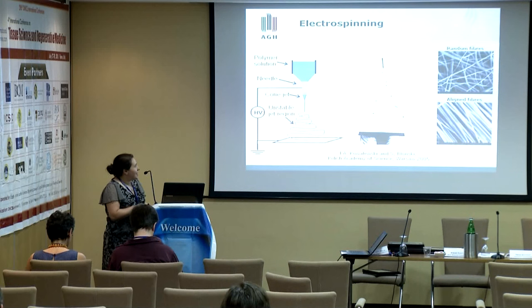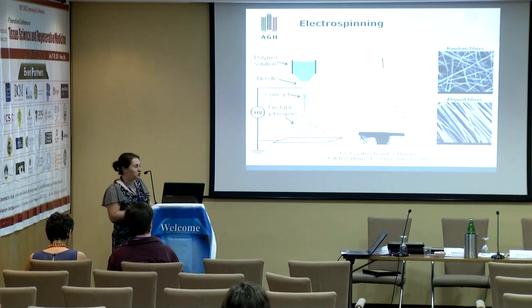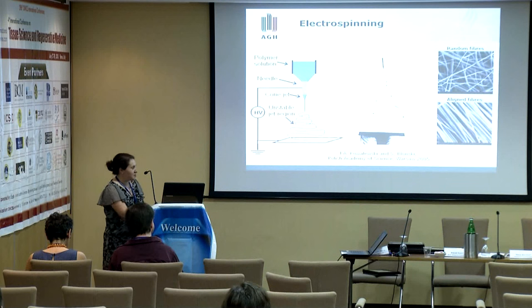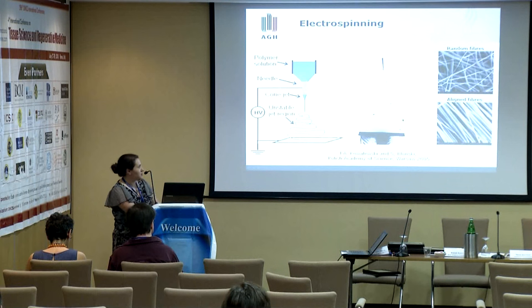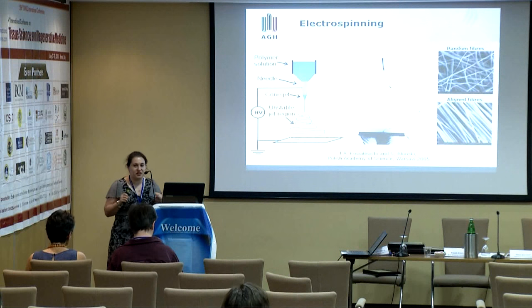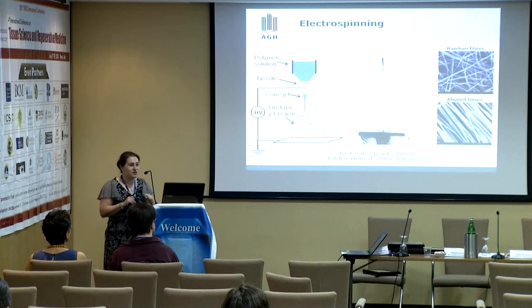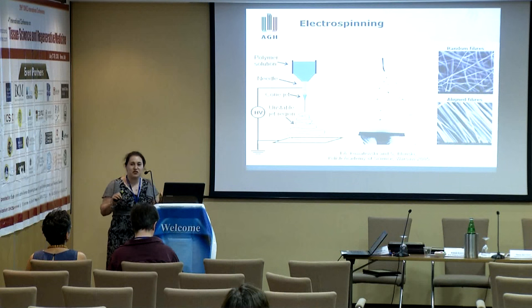We push the polymer solution through a nozzle where we apply high voltage, and due to electrostatic forces we have formation of the cone jet and the spinning region. During the spinning region there is a stretching of the jet, and during the stretching the solvent is evaporating, and what you produce are solid nanofibers.